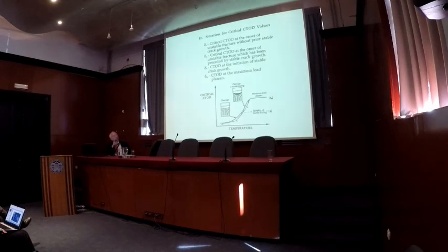In CTOD analysis, there are four ways of getting CTOD, and they're given different letters. One is getting a critical crack size, which is brittle fracture before any ductile crack growth occurs, delta sub C. Then if you get ductile cracking before the critical crack size, they call it delta U. If you reach maximum load, the most usual thing is to say CTOD at maximum load is delta sub M. And if you want to do an R curve approach, then you would get a delta I. So those are four methods for CTOD. Now you have to read a CTOD standard to really get into that. That's fairly, or too complicated just to talk about in a short time.